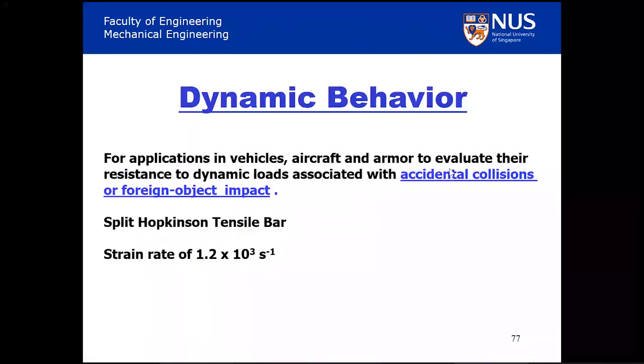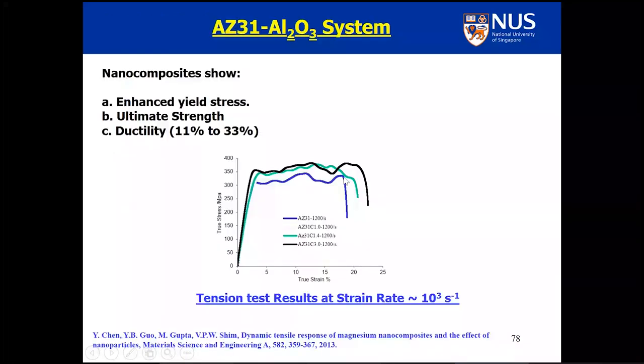And how about dynamic loading? Here I work with some of my colleagues who are experts in the split Hopkinson bar, where we test the materials at high strain rate up to 10^3 per second. Now focus on this blue curve, which is monolithic material, and the black curve, which is the nanocomposite. When you apply the high strain rate loading, your composite increases the strength and also shows higher ductility. These properties are very important for the transportation sector, because when you enter into a collision and your system shows higher strength, that means the survivability of the passengers and the driver in the car is much higher. So this is something which the transportation sector looks into.